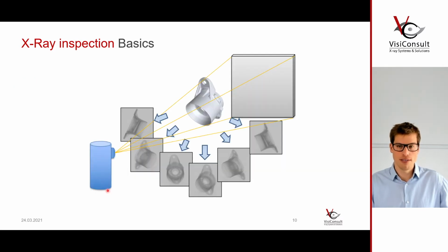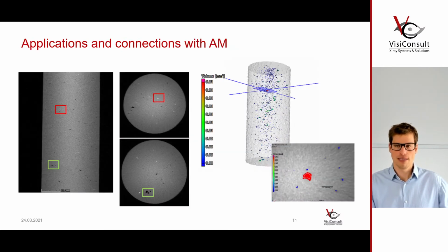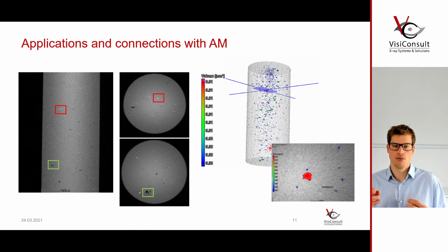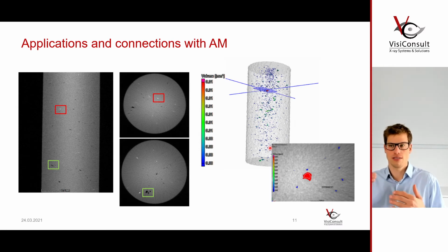So in a very brief explanation, what does computed tomography do? You have an X-ray tube, you have a detector, you have a part, and you turn this part inside the X-ray beam. You acquire a lot of X-ray images along the way, and you reconstruct them in what you have just seen as the virtual digital twin of your part, which you can inspect. So this, for example, here is a scan of a tensile probe that has been additively manufactured, just to check before you apply cyclic loading and before you see where it actually fails. You want to calculate where it should fail to see if that works.